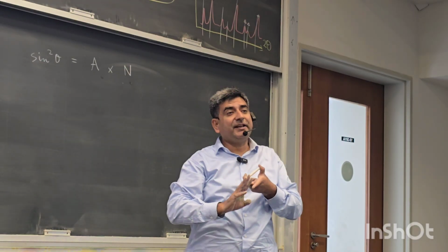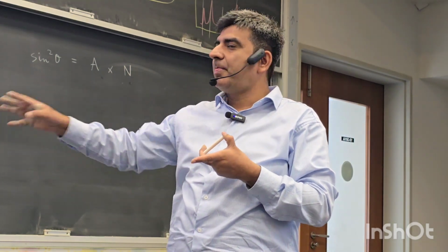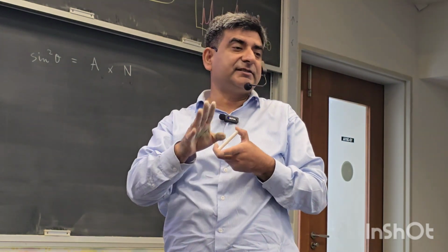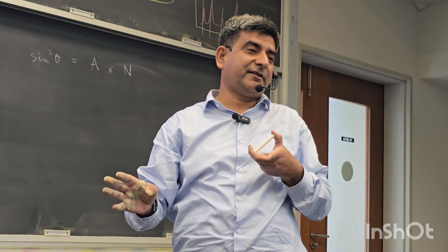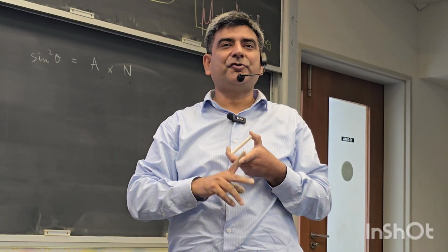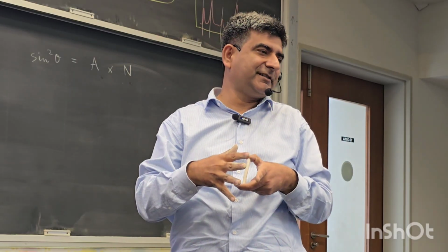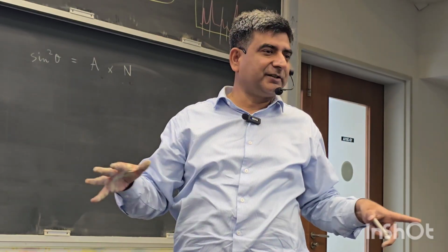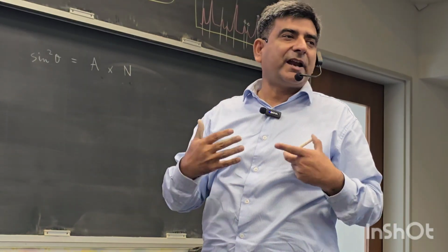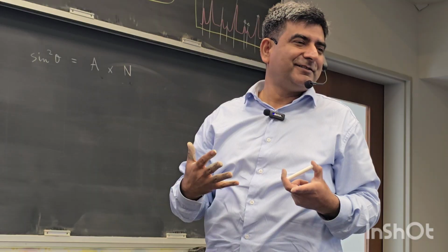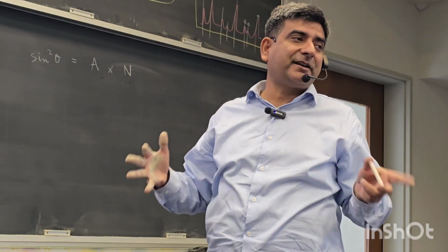However, you can see whether the HKL planes that are reflecting follow the conditions, the absences that we have. Certain reflections are absent for face-centered cubic. For face-centered cubic, you need to have them all even or all odd. If you have mixed indices, those reflections are absent. These are called systematic absences. Body-centered, they must all add up to even; odd sums are systematically absent.